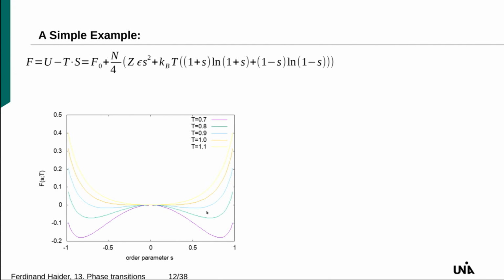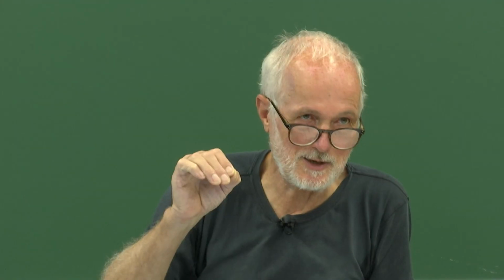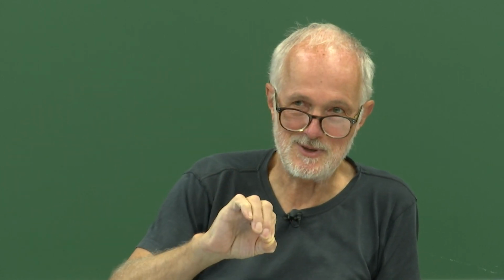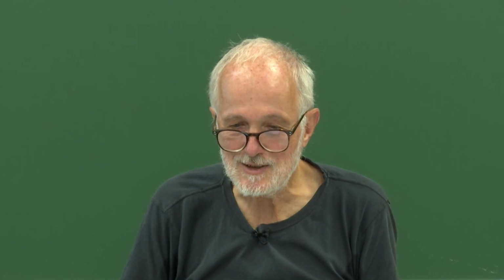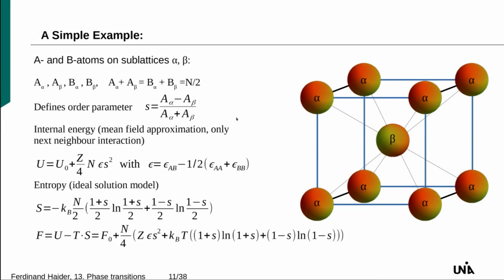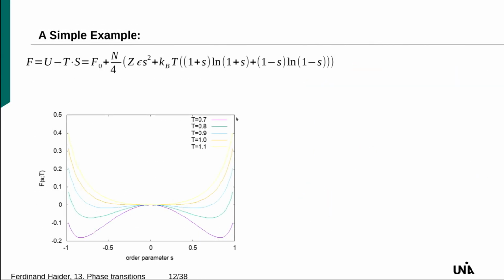Plus minus just means that I can put the copper atoms on the corner side and the zinc atoms on the body centered side, or I can put the zinc atoms on the corner sides and vice versa. So it's just an inversion of sign, and this is visible here in this definition of the order parameter, which can be plus or minus.